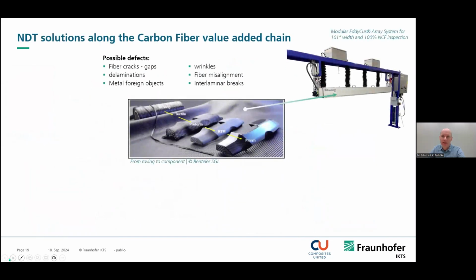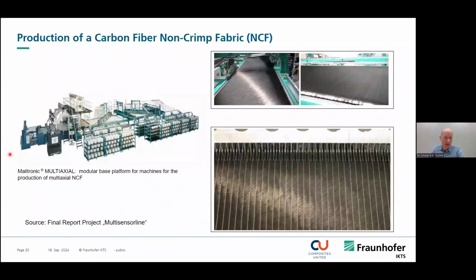So the last but not least is the novel developed eddy current array that inspects up to 101 inch of non-crimp fabric. So that's a typical size of a machine. So this machine is developed by Karl Mayer Malimo in Chemnitz. There are different fibers laid up, up to 5 fiber orientations, and then stitched together to a so-called non-crimp fabric.